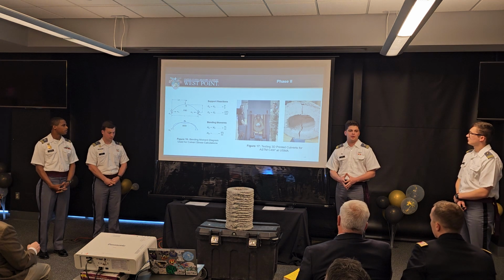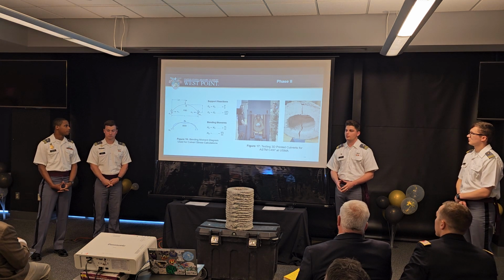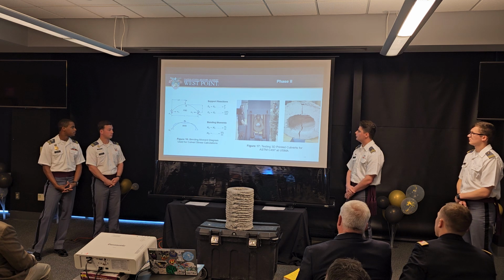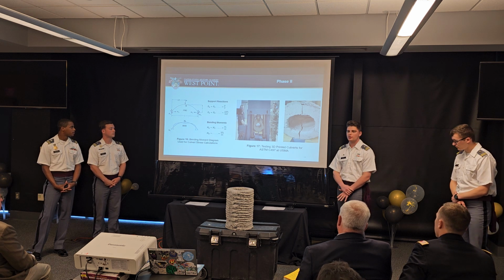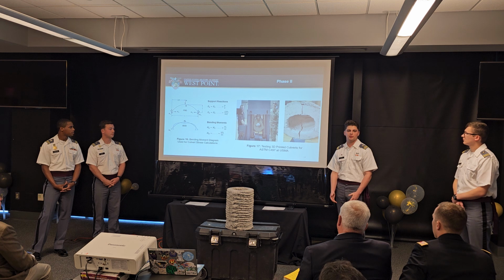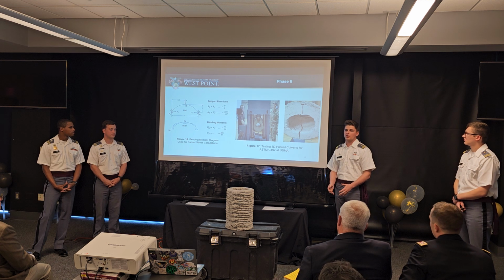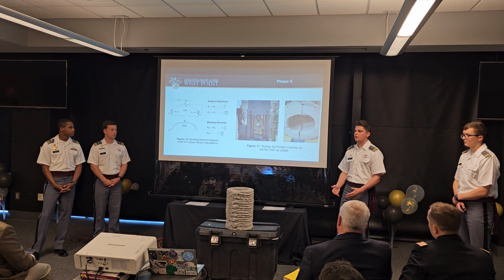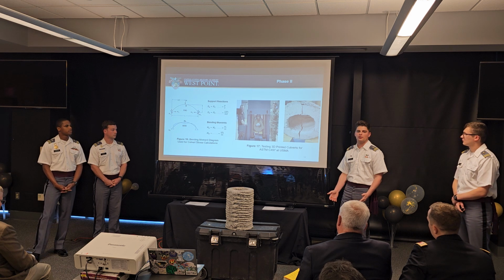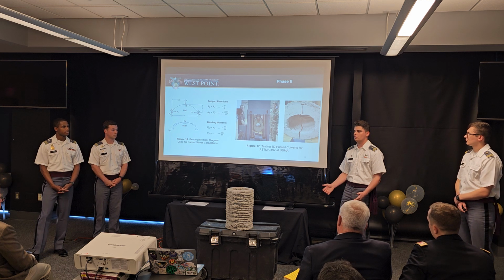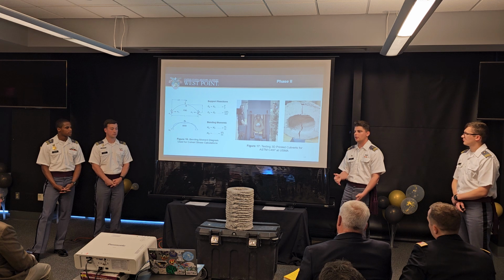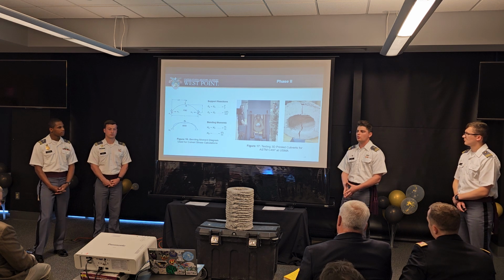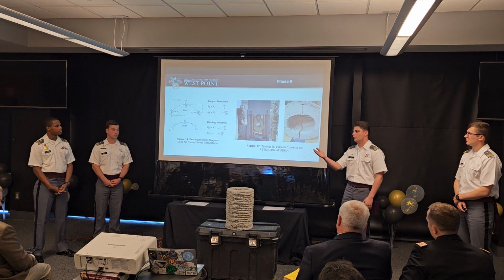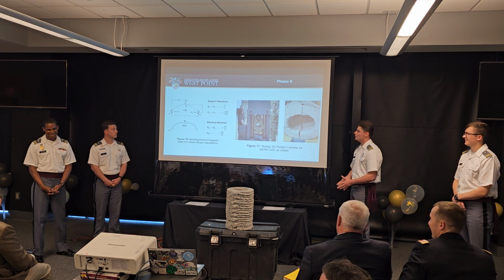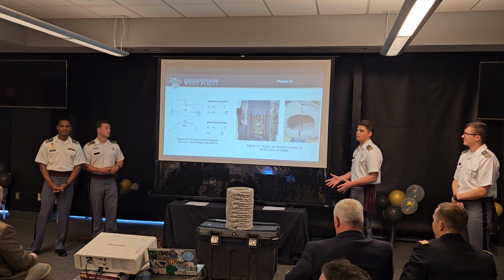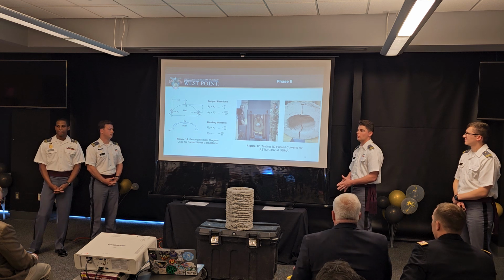As we talked about earlier, our project was split into two different phases. And in phase two, one of the most crucial aspects was the testing of these 3D printed culverts that we got from CERL. During the design process, we ran into an issue: how do we analyze these culverts? How do we anticipate how they're going to fail? It's a 3D printed shape, which is going to solidify at a different rate based on when it was printed. So, through analysis and speaking with Dr. Williamson, we decided that it would be best to make an assumption due to many different factors and treat this as an arch.